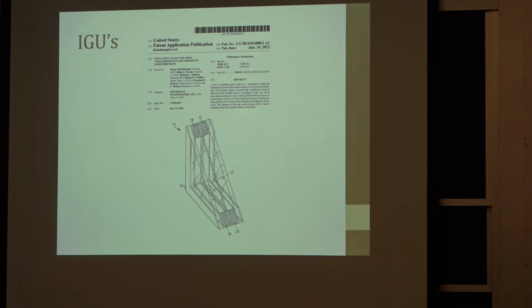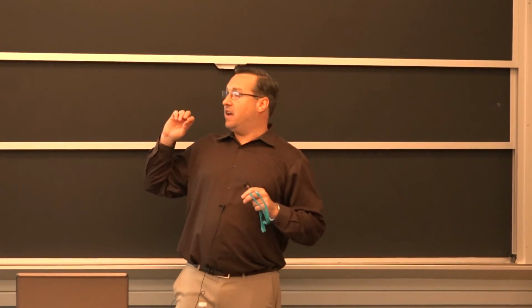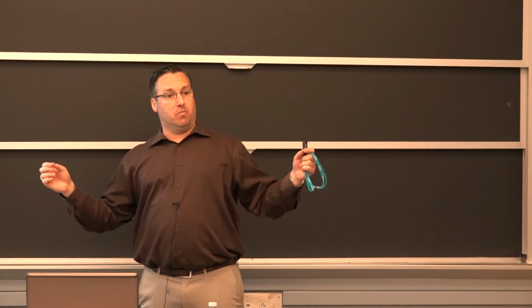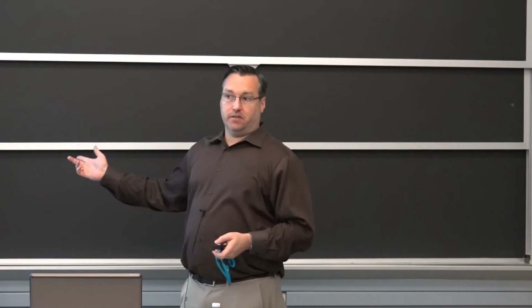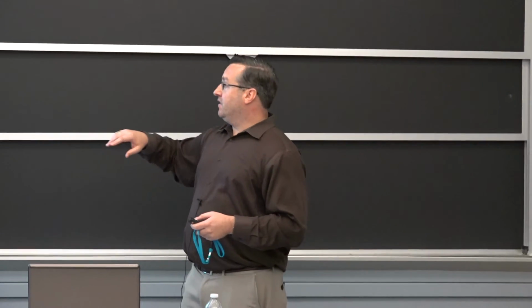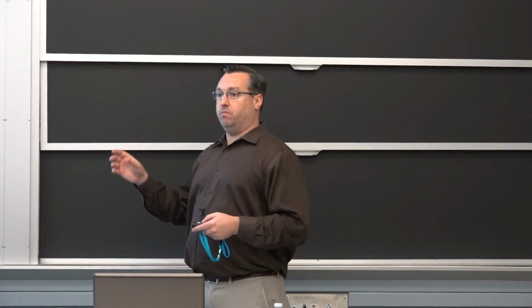And I touched on this last week when I was giving the material substitution lecture, but one of the issues related to thermal stress is as designers try to minimize this gap space and make the entire thickness of the IGU thinner, what happens is you have less gap space and things are getting hotter in that gap space, and the heat can't diffuse out of the gap space. So you can actually get so hot that it causes a thermal stress breakage in the panels. This is actually more common than you'd think to see glass breaking because of thermal stress.